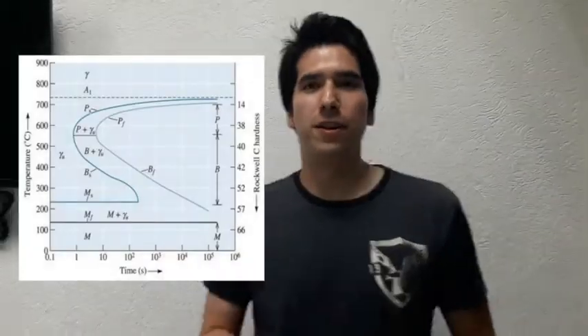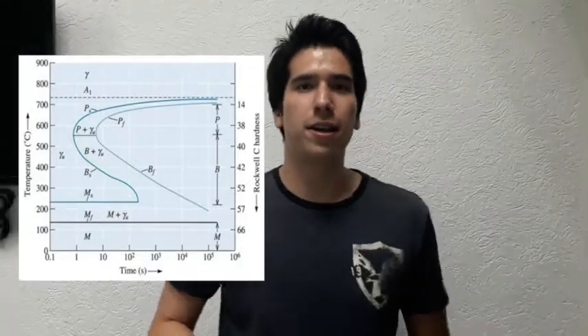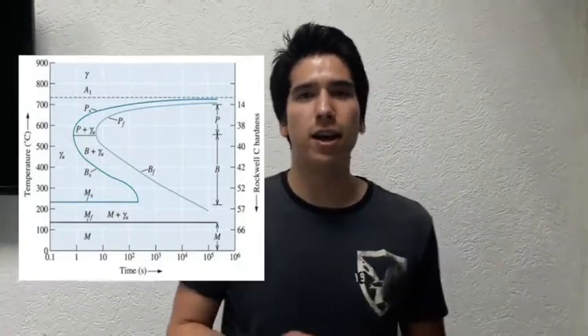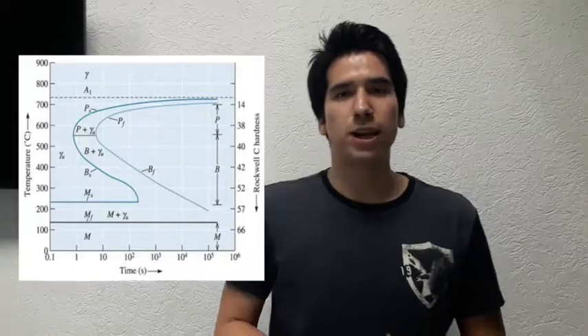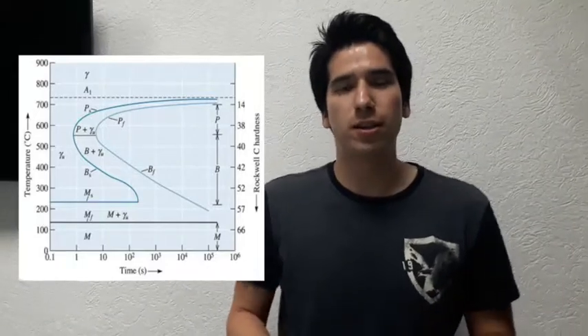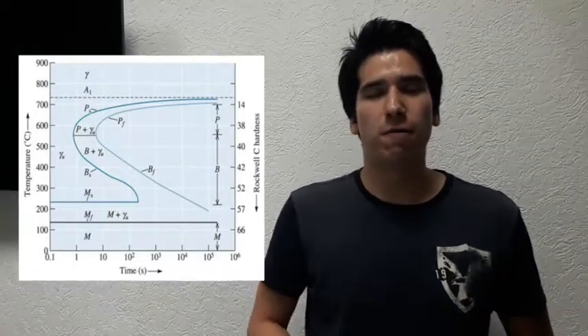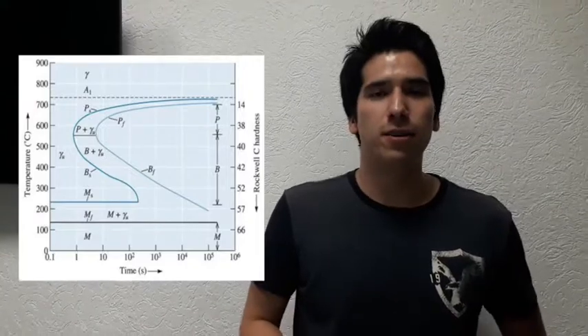For the first and second stages, at 900 and 800 degrees, we can see that the Rockwell hardness is lower than 14. And for the third stage, at 200 degrees, we can see that it is at 57 Rockwell hardness.